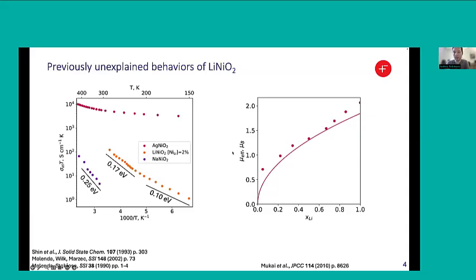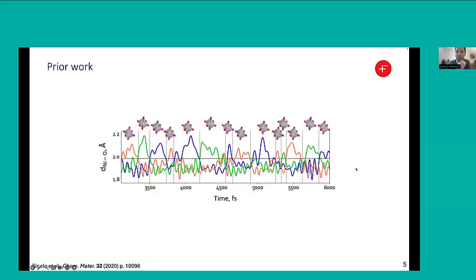And the second one is the evolution of the average magnetic moment as the lithium is taken out of the cathode upon charging. So this curve would describe a nickel 3, nickel 4 redox. This would be the normal expectation. And in particular, when this material is pristine at the far right of this plot, its magnetic moment is too high to be all nickel 3 plus. And by the end of the talk, I hope we can explain this. But starting with atoms,